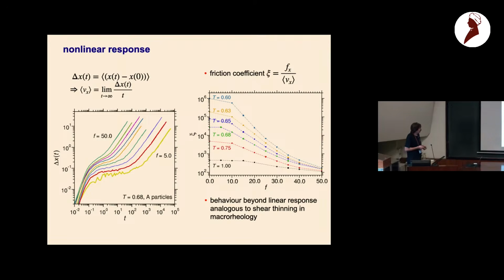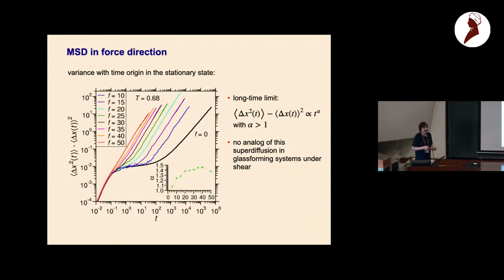One very exciting result here, a kind of fingerprint of microrheology, is here the MSD, again in force direction corrected by the drift motion, again for this temperature 0.68. We see, for comparison, the equilibrium curve. First of all, these curves at finite force agree with the equilibrium curve, and then we have this deviation.